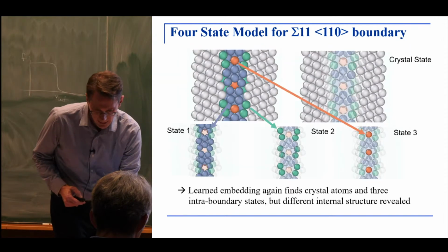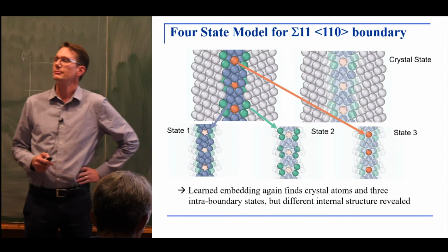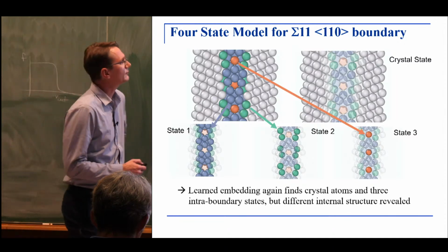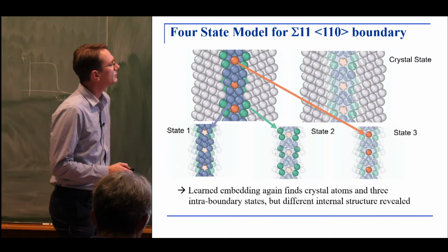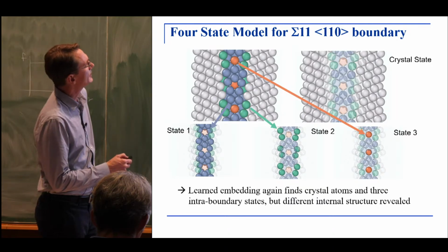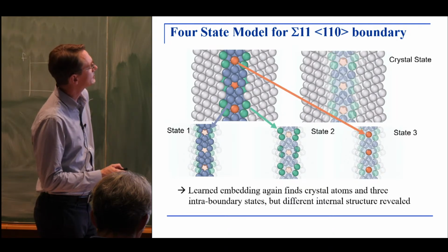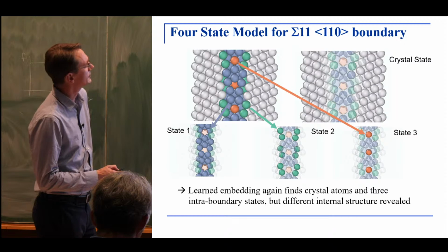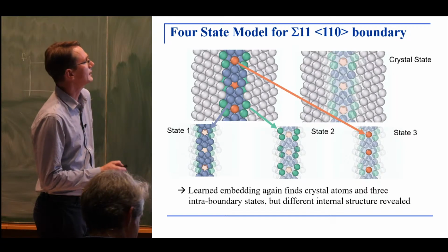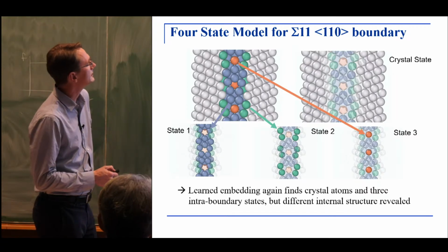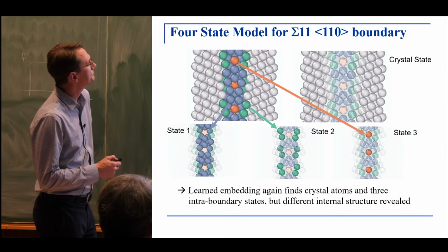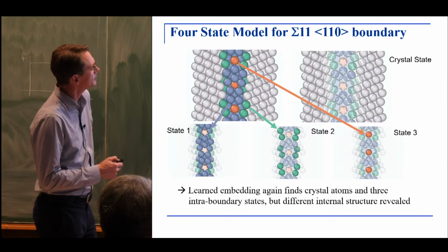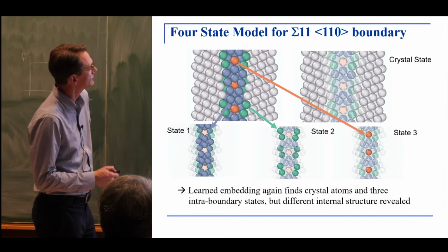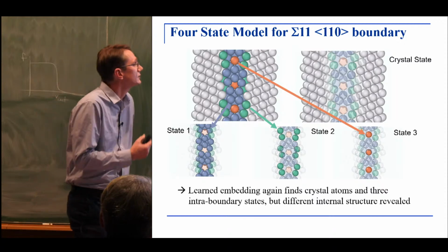This is a picture of a different boundary, the so-called sigma 11 one. It's still a symmetric tilt boundary, and you see that the angle of mismatch is slightly different. Again, our model finds state 0 to be the crystal state, and the other three states are the defect states, the grain boundary states. And we have a different partition now of the grain boundary because of the different internal structure.